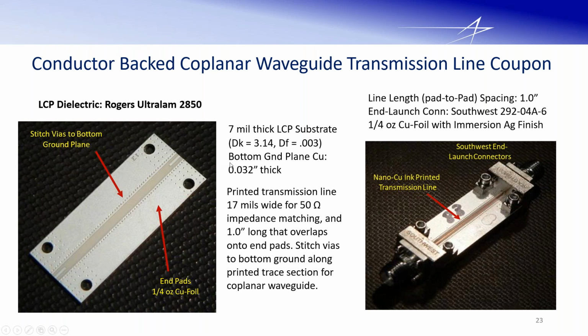It has some silver pads, and you're printing your transmission line right across it. So this coupon, the substrate is a liquid crystal polymer material, fairly low dielectric, low loss. It's got a bottom ground plane, fairly thick. It's a 1/4 ounce copper on the top, and it has an immersion silver finish that we really like for this. We don't like using nAg at all for RF stuff. There's a significant degradation in the performance with nAg, so we try to stay away from that wherever possible. So this immersion silver right to the copper has been working really nice for this.